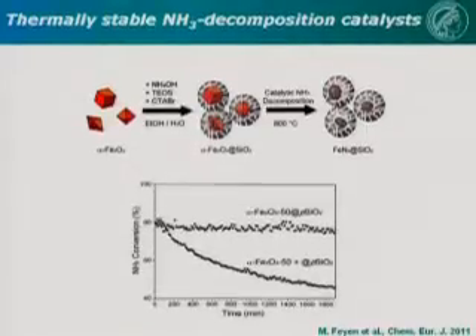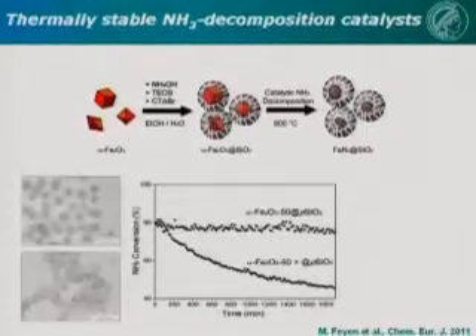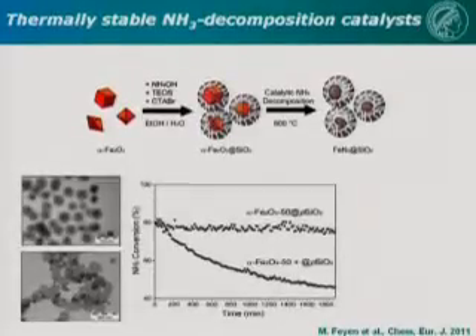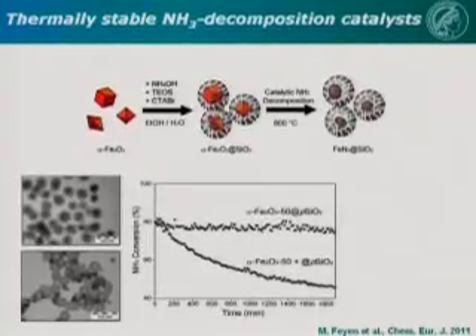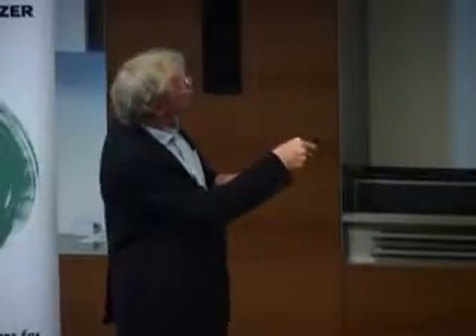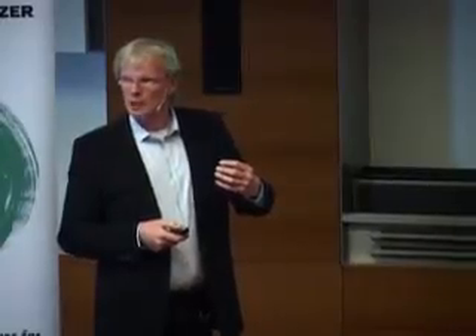And now I show you what the different catalysts are. This is the iron oxide encapsulated catalyst. So iron oxide in a porous silica shell, under reaction condition, converts to iron nitride. But Matthias Feyen synthesized the reference catalyst by taking such a sample here, coating only half of it with porous silica, the other half of the iron oxide nanoparticles he set aside. He coated the first half with silica, and then leached the iron oxide out with hydrochloric acid.